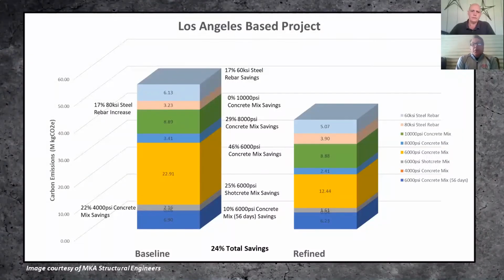The design team reduced 24% of the total project embodied carbon footprint at zero cost add. There was no cost add at all. And that's after accounting for the carbon from barging aggregate from the Pacific Northwest down to LA. On the PT slab mixtures alone, they reduced the carbon footprint of the mix by 47%.